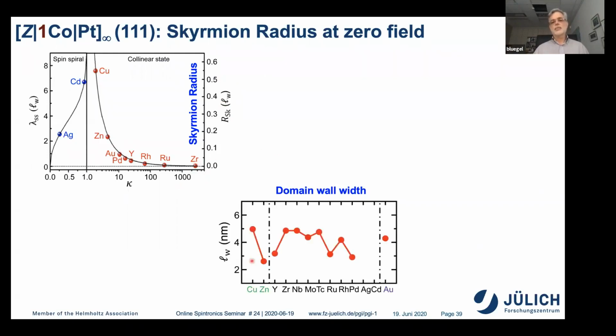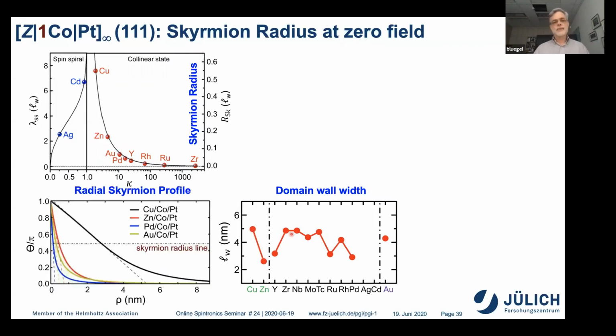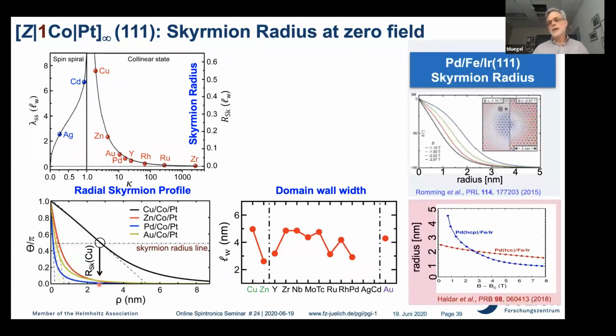And if we now look at the domain wall width, which is between 3 and 5 nanometers, you see that we calculate here the profile of the skyrmion. You see, this is this theta pi half line. And then you see the skyrmion radius is in the order of the domain wall. So it's about 2.5, 3 nanometers. And this is consistent with the experiments of Wiesendanger for monolayer type skyrmions, which we have calculated.